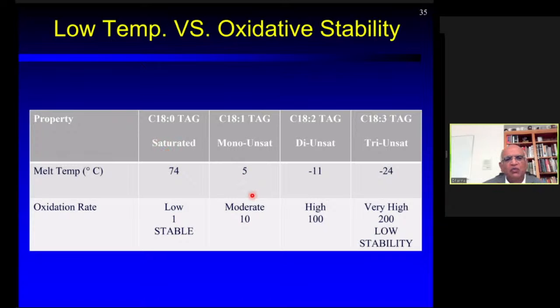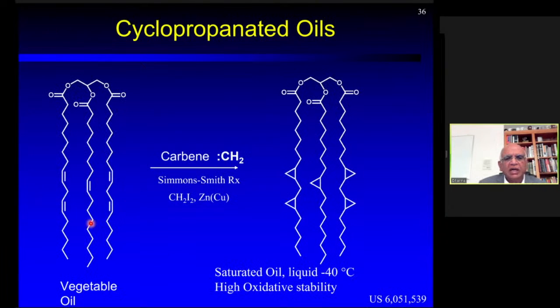So if we could do something very similar to that, create a kink in the middle of the chain, it will break the molecular packing to give the right flow properties, and it is saturated, therefore it will have good oxidative stability. How we accomplished this is shown here. We converted these double bonds into cyclopropane groups, by reacting with carbene, by doing a Simmons-Smith reaction, which is shown here, and that put a kink in the middle of the chain, and that provided the flow properties.